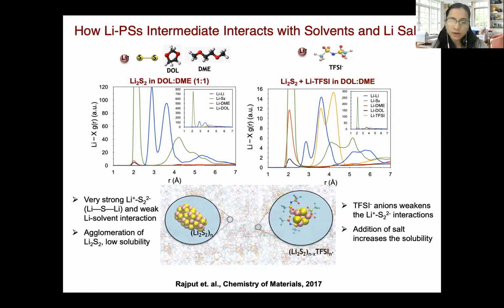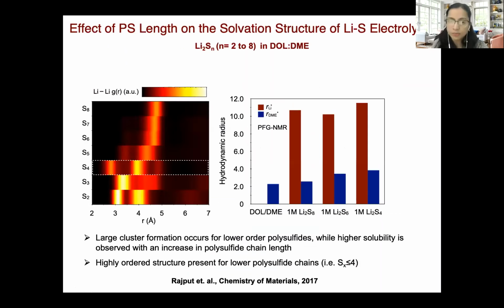However, like I mentioned, there are other lithium polysulfide species also present in the solution. So it's important to study what's happening with them. So we looked at the effect of polysulfide chain length. This is the exact same plot as I just showed in the previous slide. It's just a heat map showing different peaks as a function of polysulfide chain length. And we found that these smaller order polysulfide species like S2, S3, and S4 have a strong tendency to form aggregates in the solution. And this tendency decreases as we increase the chain length of polysulfide.